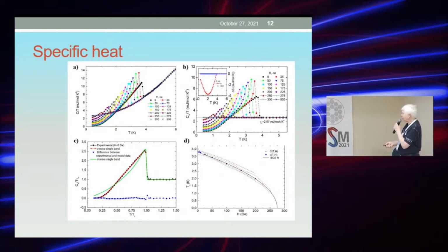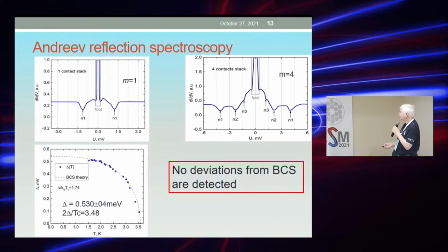It can be analyzed and we can calculate the height of the specific heat jump. From these measurements, we can plot the Tc versus magnetic field plot, which doesn't show anything specific. And from Andreev reflection spectroscopy, we also trace the evolution of the superconducting gap as a function of temperature, and we didn't see any substantial deviation from the BCS theory.